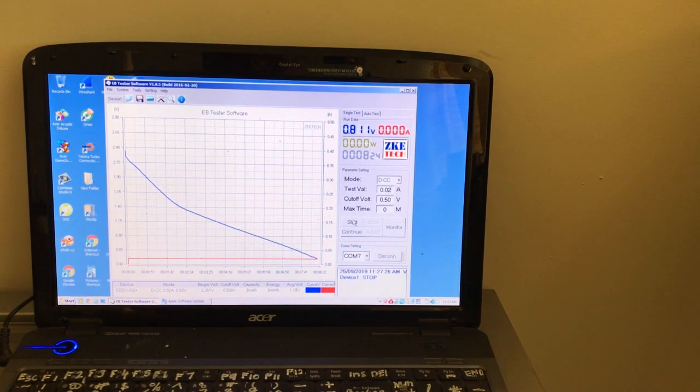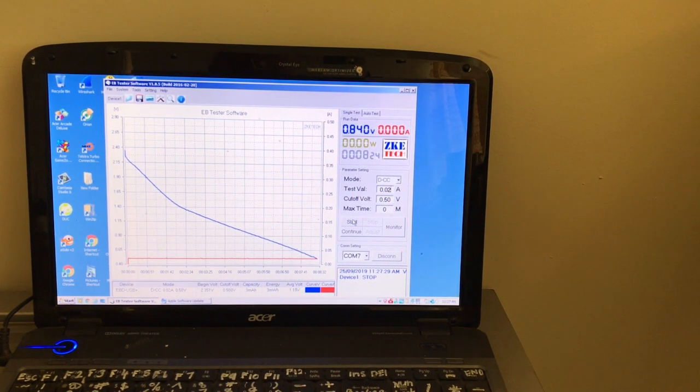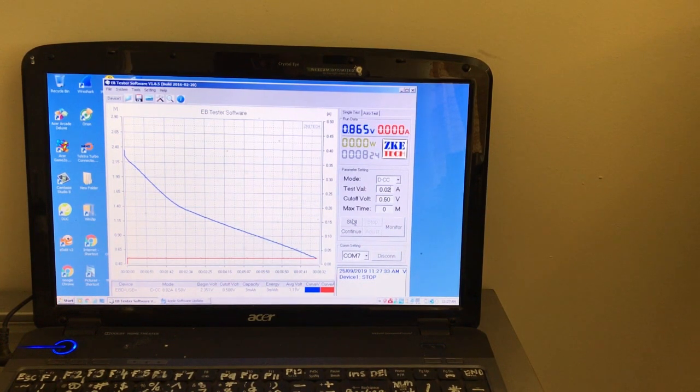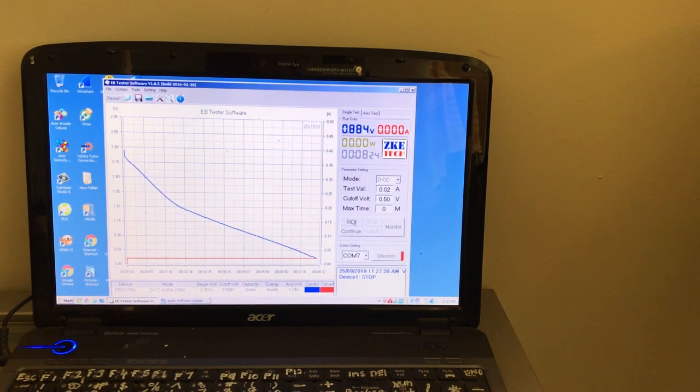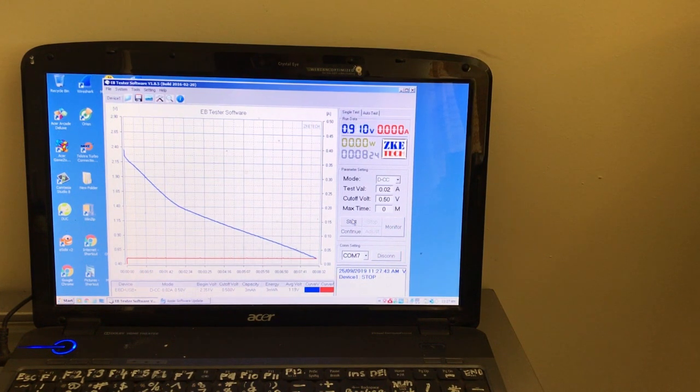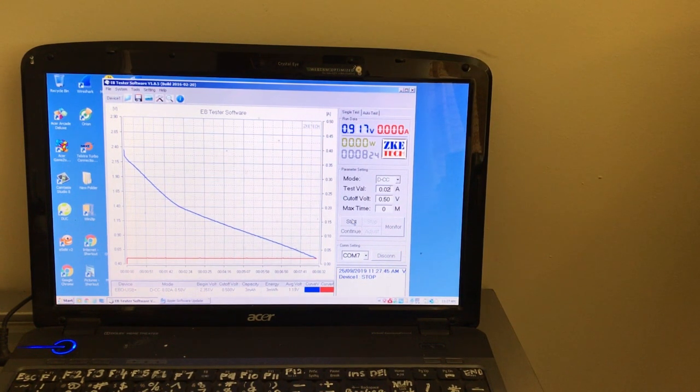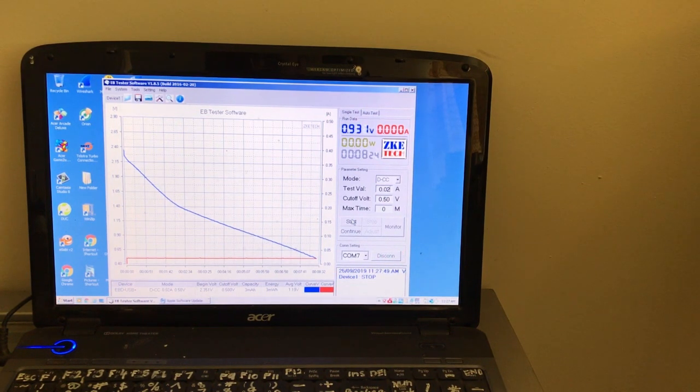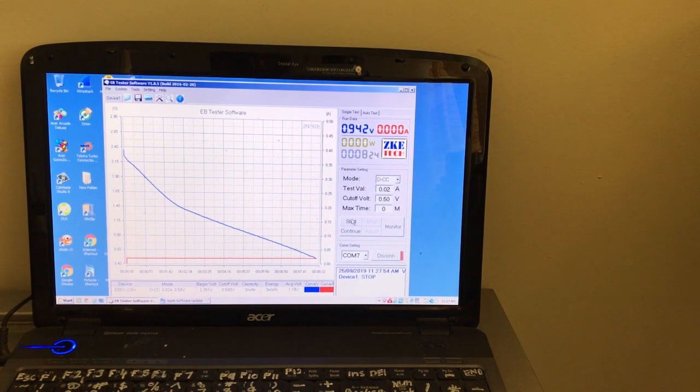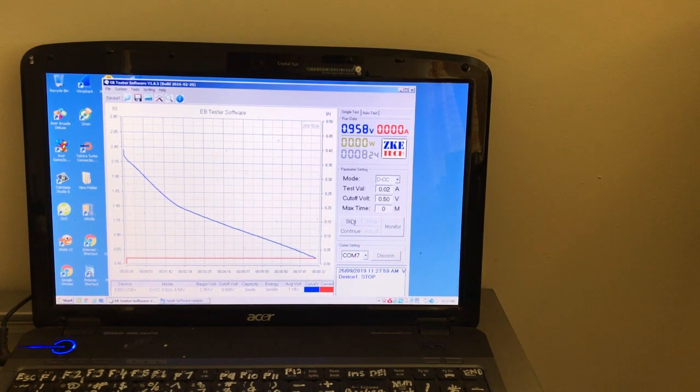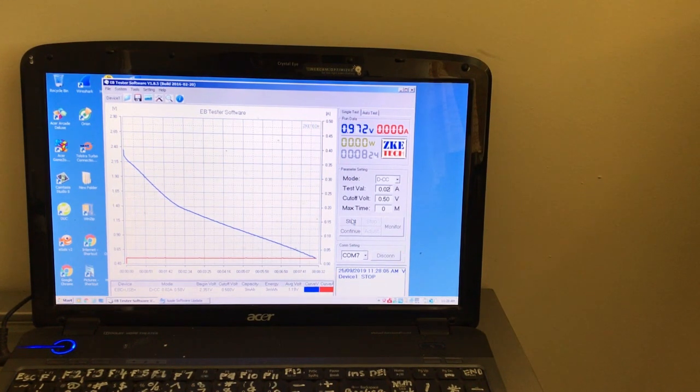Eight minutes, 24 seconds runtime. There you go. I would have thought it wouldn't have but it may hold more electrolyte because it's a thicker material than the tracing paper perhaps. That was soaked in the same solution at the same time for the same duration. So I would imagine it's got a higher electrolyte content. They both are coated twice. Depending on the material, it was both all dry. So one's a bit slippery, the surface, and the paper towel's a bit more windy with the coating.